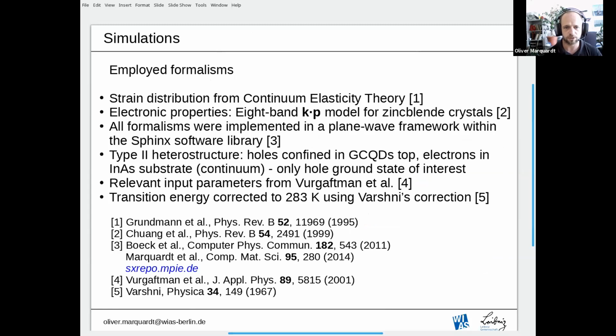We have employed continuum elasticity theory and an 8-band k·p model for zinc blende crystals. All that was implemented within a plane wave framework of the Sphinx software library. Let me note that the system we are talking about is a type 2 heterostructure, so the holes should be confined in the quantum dot, the electrons in the substrate. So we had a look here only at the hole states because these are then the ones of interest. All parameters for our simulations were taken from Vurgaftman's paper from 2001, and we have then applied Varshni's correction so that we correct our energy values to the temperature of the measurements.